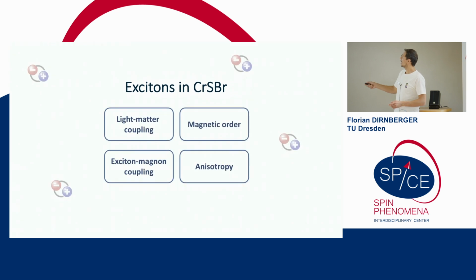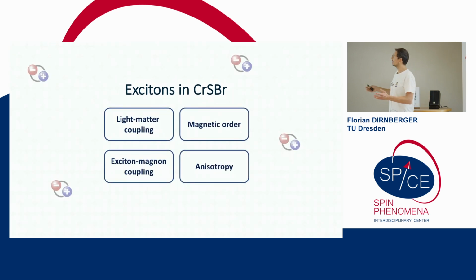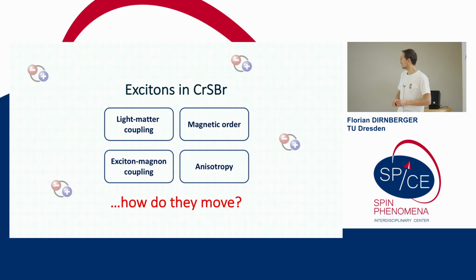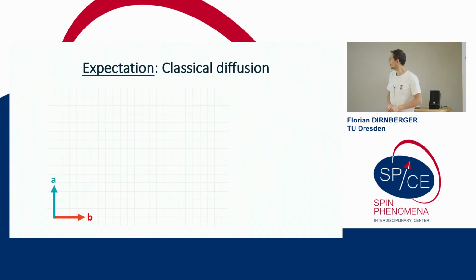So in chromium sulfide bromide, we have found a material that has excitons that couple very strongly to light. They couple with the magnetic order, with excitations of that magnetic order. And on top of that, as we've already seen quite a bit, especially in Mike's talk, the electronic structure of this material is also highly anisotropic. All of these are good reasons why we're so interested in understanding how the excitons, once they're created, actually move in this crystal.